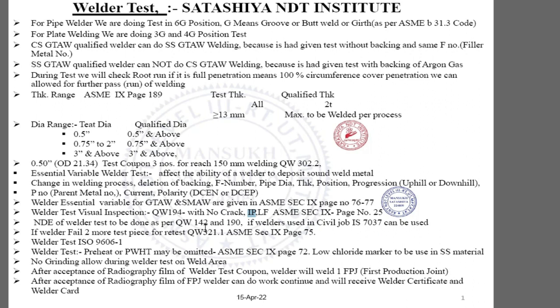The welder test examination normally is done as per QW142 as well as QW190. If the welder test is for civil work such as round bar welding, in India we follow IS 7037 (Indian Standard 7037). If a welder fails the visual or radiographic examination, two more retests can be allowed. But before giving the retest, advise the welder to do practice for two to three days, and only give the test when confident — otherwise rejection will be demoralizing. Keep the welder motivated and positive.